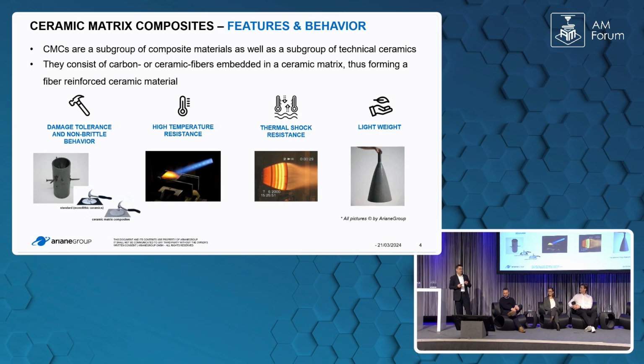For me, the most impressive characteristics are really, on the one hand, damage tolerance. So Olaf, you just mentioned the part here. You can really penetrate this fiber-reinforced ceramic with nails, and nothing happens. It behaves like wood. Temperature resistance, very, very high temperatures, meaning up to 2000 degrees C, in combination with thermoshock resistance you see here, because you can imagine if you have the boost of a rocket motor, of a propulsion system, in some milliseconds you are from 0 or below 0 up to maybe 2800, 2900 degrees C in the wall. And one additional benefit, because of the low density, is the lightweight design of the components.